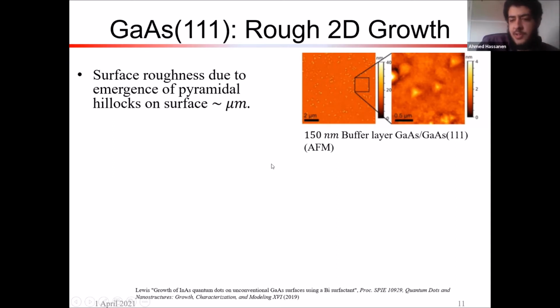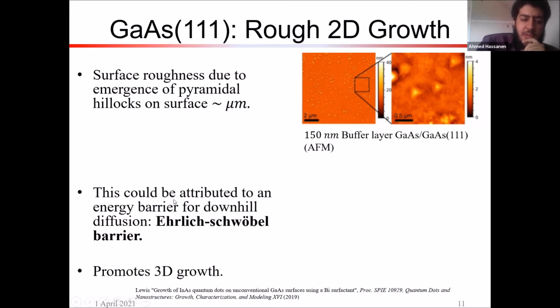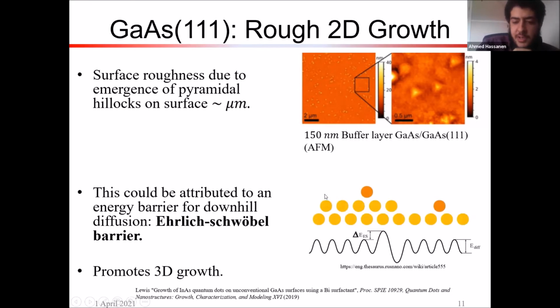This is just gallium arsenide, just homoepitaxy. These hillocks are in the range of micrometers. This could be attributed to the energy barrier for downhill diffusion known as the Ehrlich-Schwoebel barrier. You can imagine these atomic steps, and this atom is falling on the surface. Instead of diffusing downhill and creating normal 2D growth, it's sticking to the top because it can't diffuse downhill due to this Ehrlich-Schwoebel barrier. And so this barrier really promotes 3D growth. So this isn't good, of course.